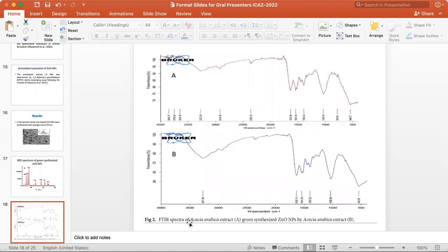Later on, FTIR spectra of the aqueous leaf extract as well as the nanoparticles were recorded. In figure A, you can see the FTIR spectrum of the plant leaf extract, and B is the spectrum for the zinc oxide nanoparticles. If we compare them, characteristic peaks indicating the presence of different functional groups have been shown here.